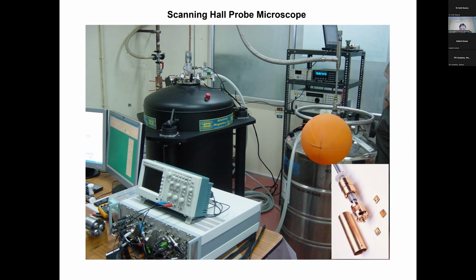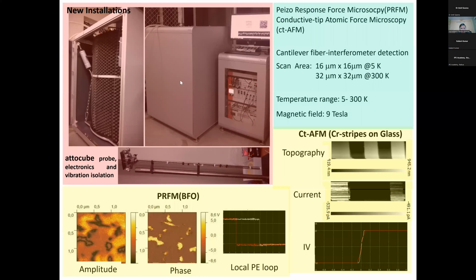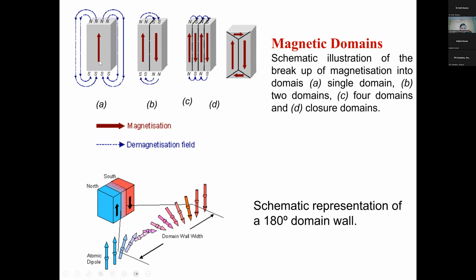And now the beauty, this is what I was saying. See, normally it's like a student scale. For students, we used to explain it. If you take a magnet, these magnetic lines of force are like this. This much is lost. If you keep another magnet down, then the sideway loss is avoided, only top and bottom. And at top and bottom also, if you put keepers, then it will be like this. It happens naturally. Instead of a single domain, it forms multi-domains only to preserve your magnetism. So the demagnetization field, otherwise it will demagnetize.